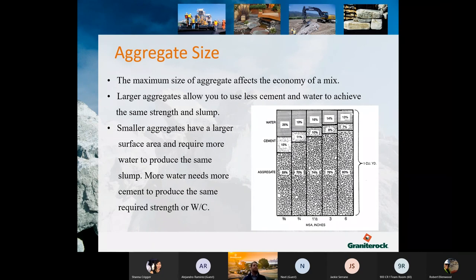So with aggregates, there are different sizes. The maximum size of the aggregates do affect the economy of the mix. Here's a little table to represent that. Larger aggregates allow you to use less cement to achieve the same strength and slump. The reason being, smaller aggregates have a larger surface area and require more water to produce the same slump.